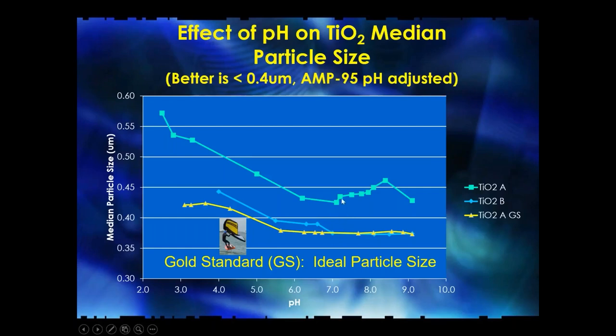If we take a standard titanium dioxide commercial slurry and we run the particle size distribution as a function of pH, we can see that it's 0.4, 0.45. And somebody's going to say, well, wait a minute, Glenn, you told me that the ideal particle size is 0.35. Well, that depends on the pH, it depends on the dispersion, it depends on whether you sonicate the sample, it depends whether you were working with dry product. Now, if you work with dry product and slurry it yourself, you'll find that the average particle size will change according to what dispersant and how you grind it.